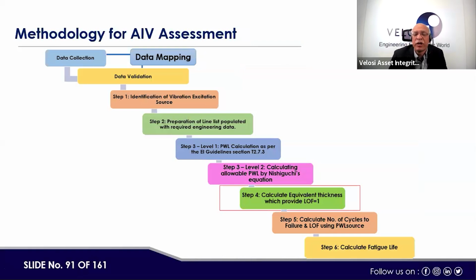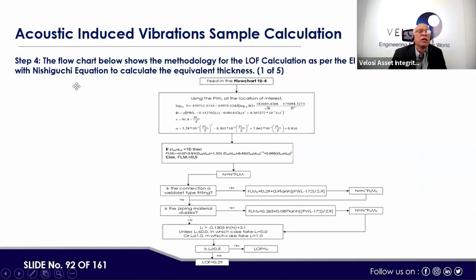Then calculate the equivalent thickness which provides LOF1. Here we have used the flow chart showing the methodology of LOF calculation as per EI guidelines with the Nishiguchi equation. You can use PWL which is 175 or you can use 180, and the thickness formula, and with that combination the number of cycles for Weldolet kind of small bore connections or Sweepolet kind of small bore connections, because with Sweepolet we can get extra number of cycles by a factor of 2.57 times as compared to the Weldolet. It means Sweepolet is a better design as compared to a Weldolet kind of small bore connection.